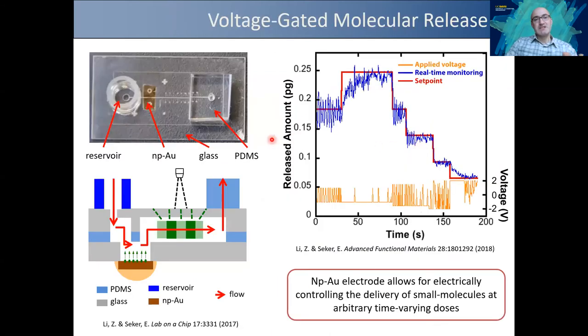So I mentioned that the surface is really important for controlling the release. One thing you could do with the electrode is, since it's electrically conductive, you can actually now use electrostatics to control the drug release. Fluorescein, for example, is a fluorescein salt. So when it ionizes, fluorescein is negatively charged. If you pull a positive potential on your electrode, nanoporous gold, with respect to a reference electrode, basically you can electrostatically stabilize the fluorescein on the surfaces. So you can load a lot more fluorescein even on these surfaces. And if you now switch it to a negative charge, you can push the fluorescein molecules out.